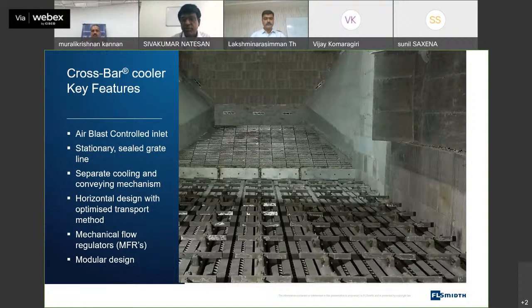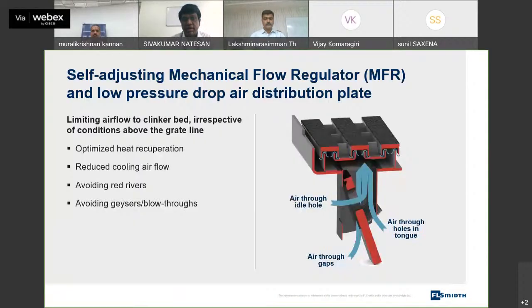Even after operations of a few months, it is not going to deteriorate. And this is a picture of a mechanical flow regulator under each grate plate in a CB cooler. This acts like a separate fan, which is able to control the airflow for the clinker nature above the grate in particular. So by the mechanism of the MFR's design, the fan flow is getting distributed to the area where it is really needed, and it will not bypass to the least resistance path.